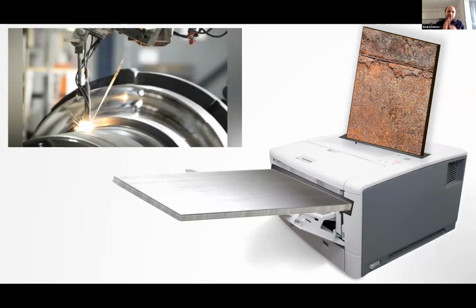Still, there are some concerns on the performance of such materials that prevent the full adoption of the LMD technology by manufacturers. We have investigated the corrosion resistance of 3 printed stainless steel grades and compared the results to their equivalent conventionally manufactured counterparts. The grades that we chose represent the different types of stainless steel we can find in the market: martensitic, austenitic, and duplex. As is well known, one of the most common corrosion mechanisms observed in stainless steel is pitting.